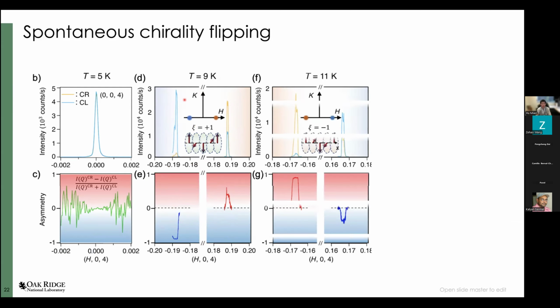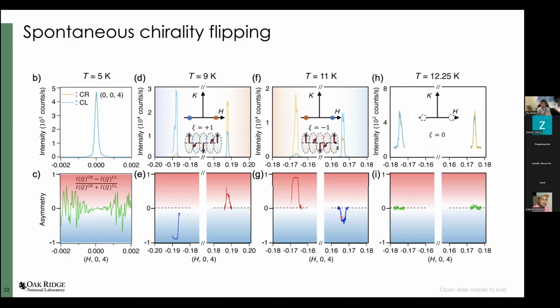But once you cross the phase transition from a single-Q to another single-Q helical spin density wave, you see the circular dichroism flip sign. So now at a negative Q, it becomes positive circular dichroism. For positive Q, it becomes negative circular dichroism. So that means the chirality, even where we stay on the same spot, is changed from positive to negative. We can further increase temperature to the achiral double-Q spin density wave phase. As expected, there's no circular dichroism at all.